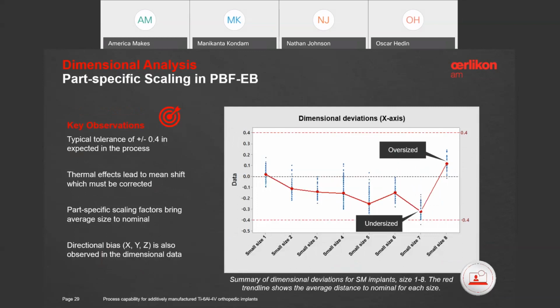This graph shows dimensional deviations from nominal for a range of smaller sized implants, which were all printed on the same machine using identical scaling factors. For a given scaling factor, the X dimensions of certain footprints tend to err on the low side of nominal, while others are slightly oversized. Others still are right on the money. Our engineers deal with this problem by running dedicated scaling builds as part of the qualification of new products, which is a costly and time-consuming process that we would certainly like to avoid. Unfortunately, the thermal effects leading to these shifts are still not very well understood.